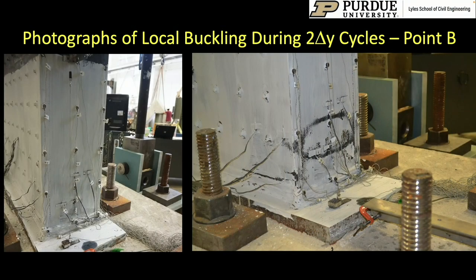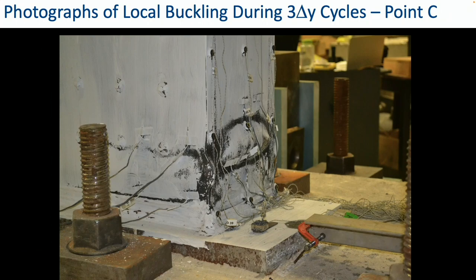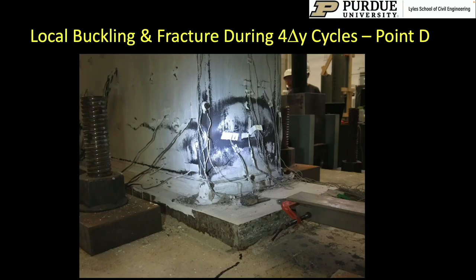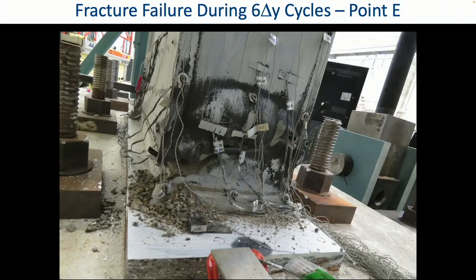I also have some photographs, for example. These are behavior during the two delta Y cycles, and you can see the initiation of compression flange local buckling, which corresponds to point B. You can also see initiation of local buckling in the webs, which corresponds to the three delta Y cycles and point C. You can also see the occurrence of fracture, which is point D, right through the flanges right here. And then finally, you get total fracture through the flanges, and you start getting the concrete to ooze out. So the experimental behavior of this system is very important to understand as well. And the experimental data does provide that information to us.